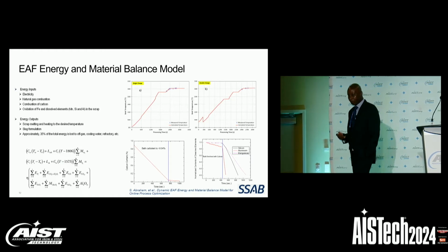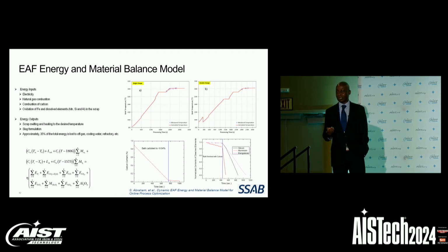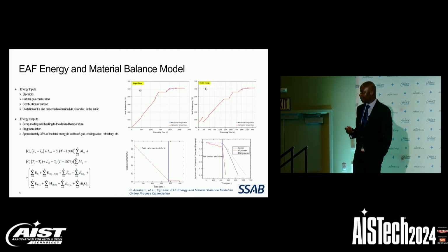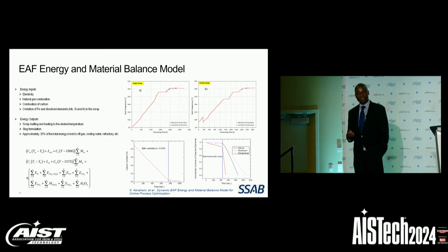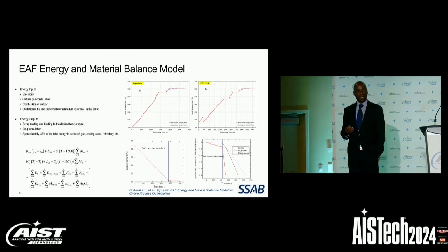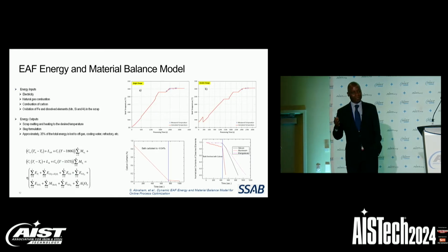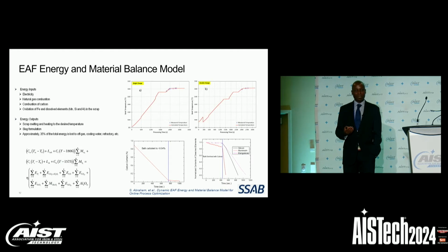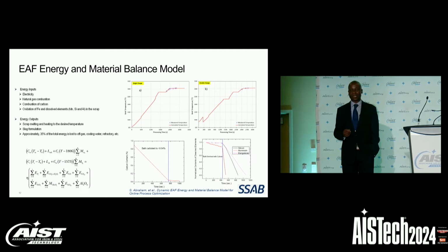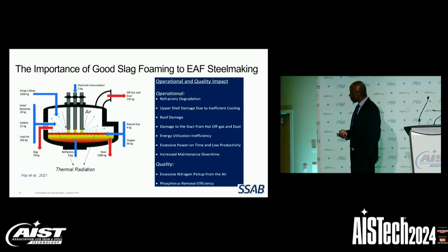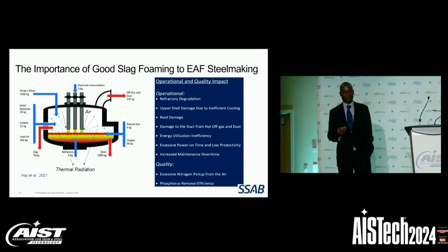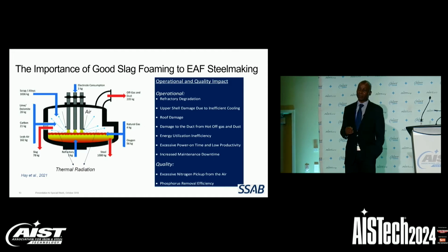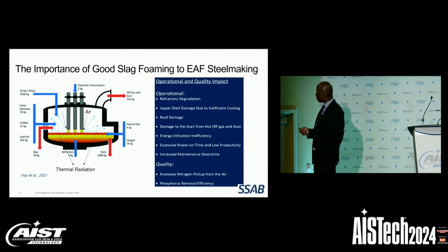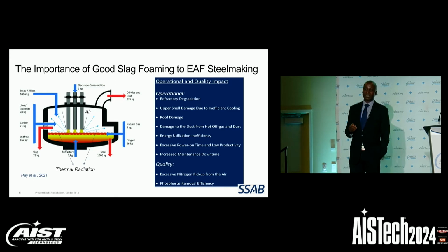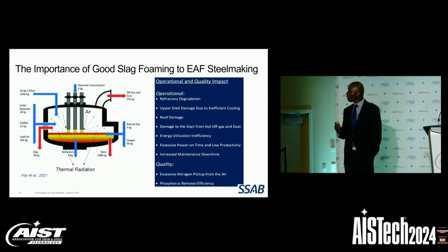In our model, we incorporated a sub-model for oxidation kinetics to predict the chemistry of the bath during the scrap melting. So our model can predict the carbon, aluminum, silicon, and manganese content of the bath. As a result, we have a comprehensive model that provides guidelines to the operators on the state of scrap melting in the furnace. Optimal slag chemistry and good slag foaming is very important for the efficient operation of the electric arc furnace. If the slag doesn't foam well, the arc is exposed, and the roof and the wall of the furnace can be damaged from the intense heat radiation from the arc.